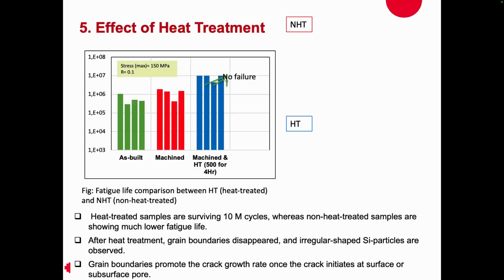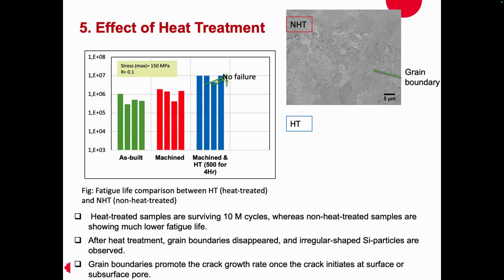Finally, heat treatment. We studied the heat treatment effect also. It's relatively simple. As-built, machined, heat treated, you get no failure. Generally, it's a universal finding: post-processing and heat treatment, peak hardening, machining, along with heat treatment will definitely improve your fatigue life, which is a clear outcome. And in this case, we can see the clear relationship.